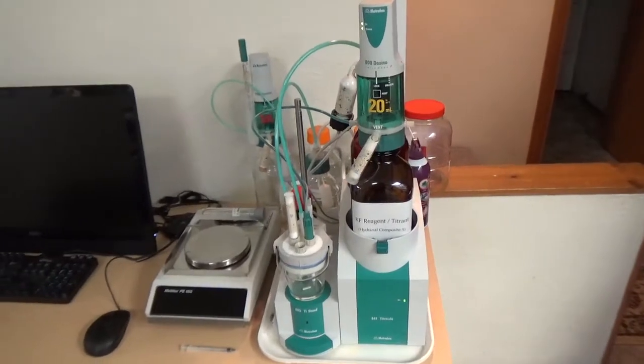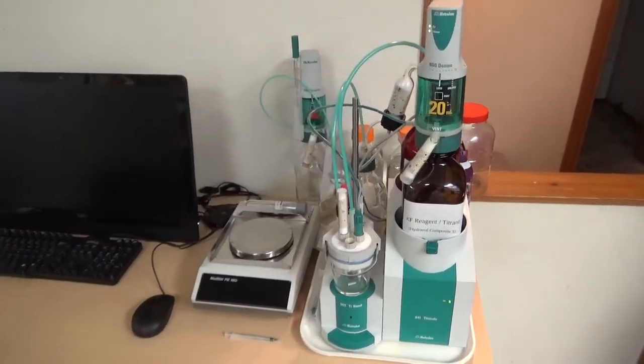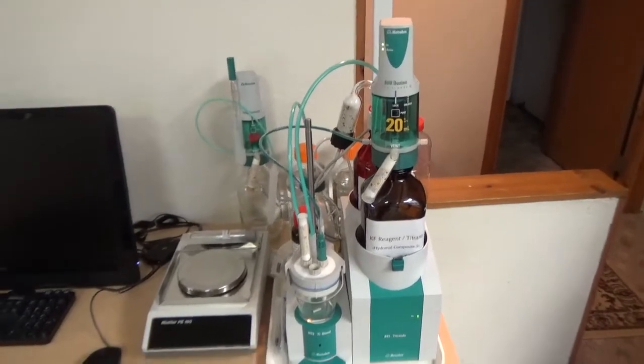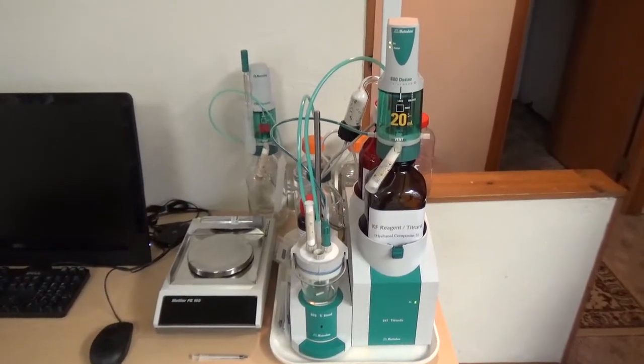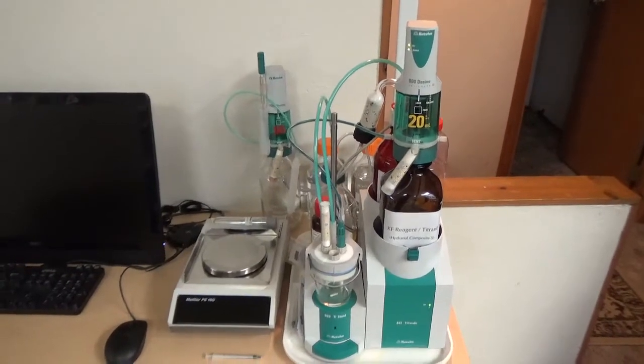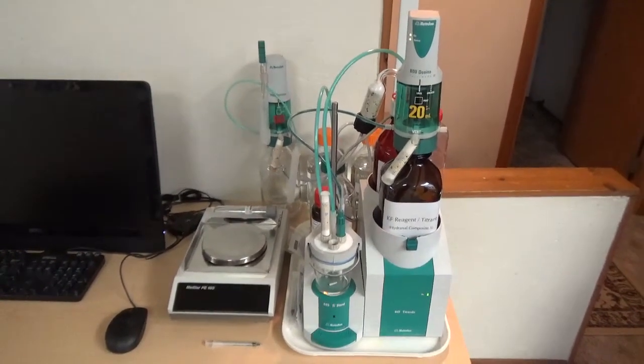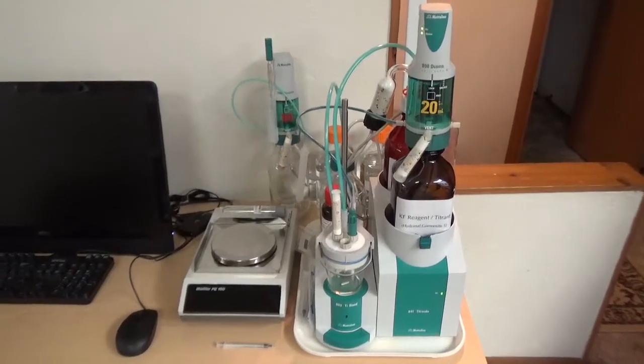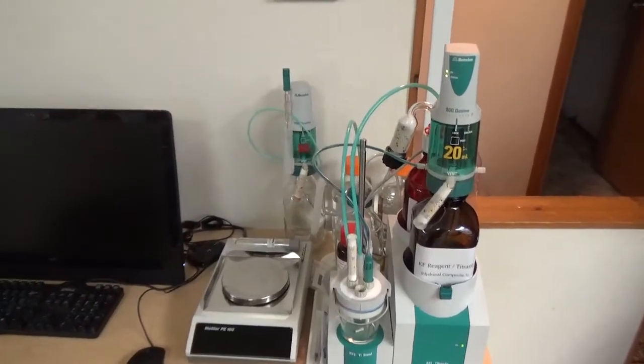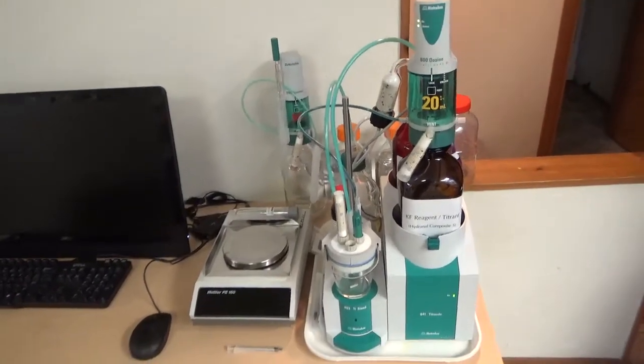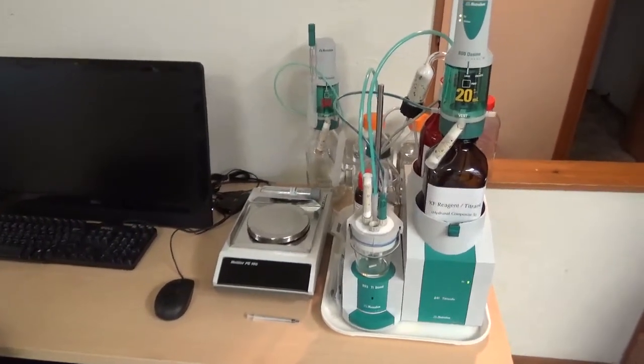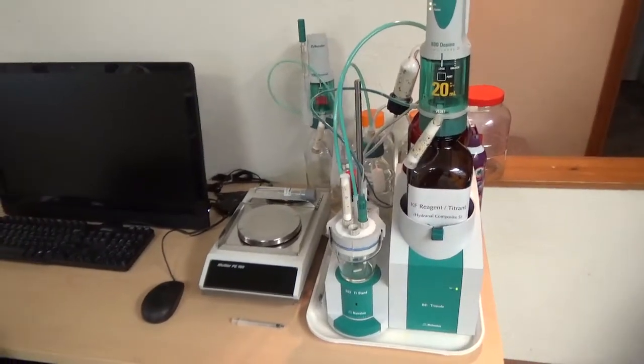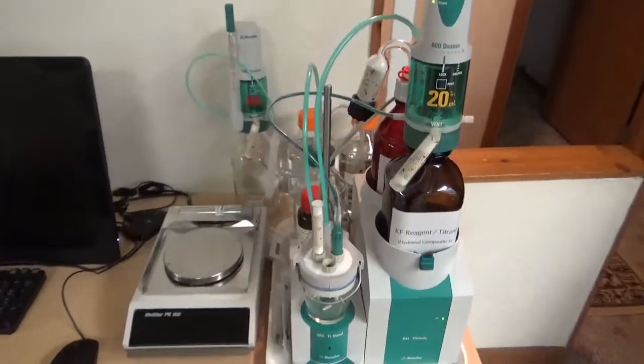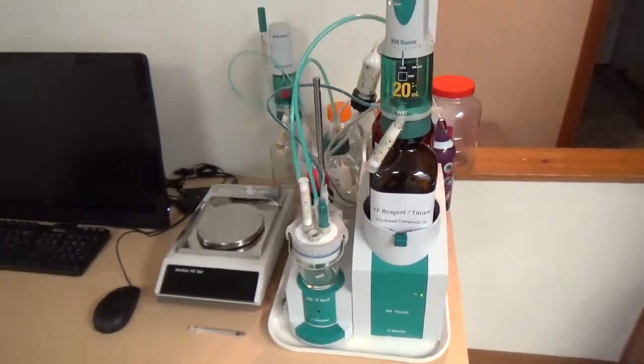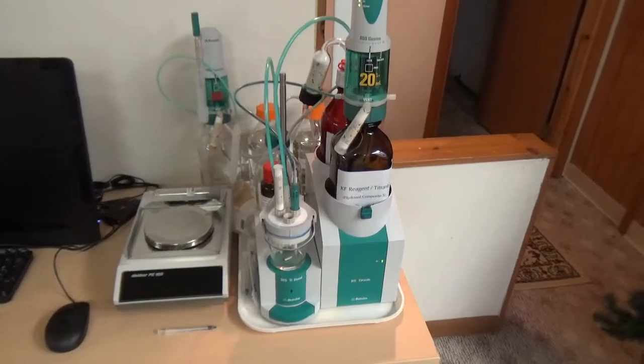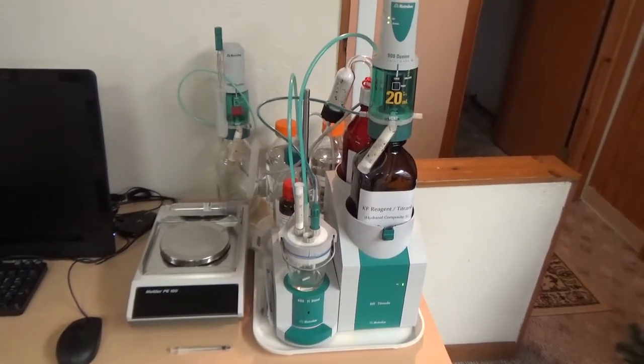Usually, to determine the free moisture content in concrete, not the hydrated water but the free water, we immerse the concrete sample in ethanol, and we do solvent replacement of moisture by ethanol, removing the moisture from the pore spaces of the concrete. We keep a small concrete sample in the ethanol solution for days in a sealed container, and then by solvent extraction we take the moisture out of the concrete, and we take that ethanol as a sample to determine the moisture content in the concrete.